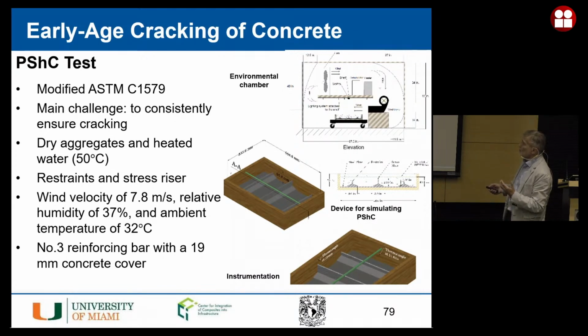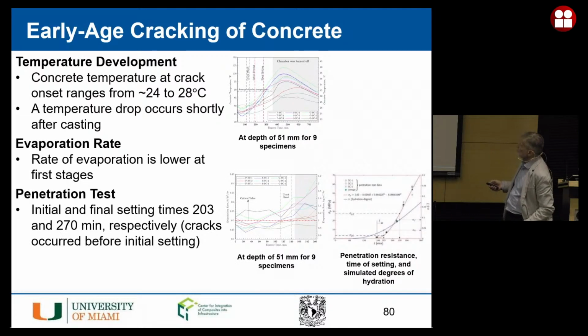In fact, we even warm up the aggregate and the water to make sure that there is a very high heat of hydration in the beginning, and that expansion that we have will then cool off and cause the cracking. So this is some of the tests. I'm just going to fly through this because I don't think you can see it. We just got a paper published as I was already in Mexico, and actually it is a collaboration with our colleagues on the West Coast, not the West Coast of Florida, but California, where they do all the analytical work to generate diagrams like this.